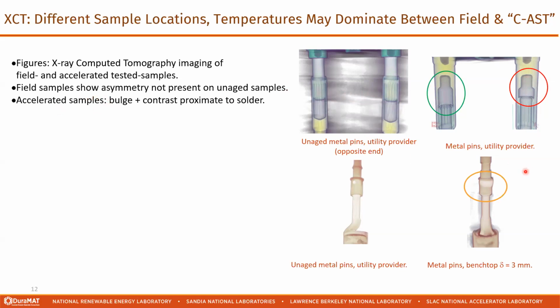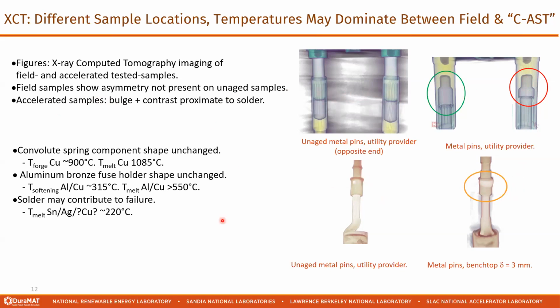In the accelerated testing samples, these are benchtop experiments, there's a deformation that's not present in the unaged sample. So if we think about it for a minute, there's a convolute spring component, and I'll show this in one of the slides that's coming up. This is made of copper. The forged temperature of copper is like 900 C. Well, we don't think we're getting that hot. These fuse holder components are composed of like aluminum bronze. This has a softening temperature of like 315 C. Maybe, but then there's also a tin, silver, possibly copper solder that's used. There is evidence, at least in the accelerated test sample, that we're approaching those sorts of temperatures.